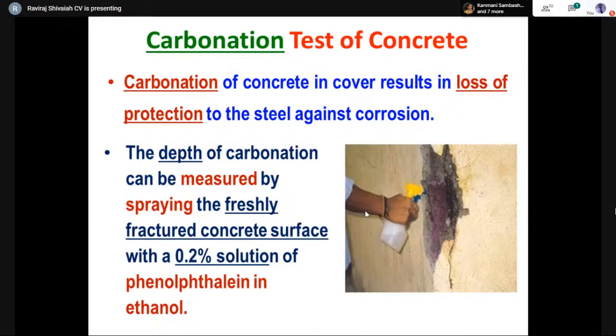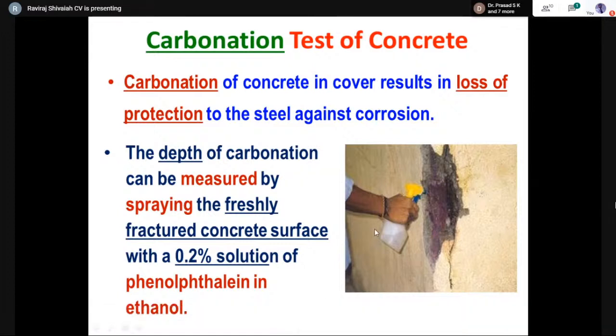Now I'm just done with the last two or three tests, very simple tests. I was talking about the carbonation test. I told you it's not good. How do we know whether the carbonation has happened or not? All you're supposed to do is break open the concrete surface slightly, about 5 millimeters, expose the concrete at a depth of 5 millimeters, take a solution of freshly mixed phenolphthalein and ethanol, 0.2% solution, and then spray it on the concrete surface. If the surface turns pink, then we need to understand carbonation has not happened. However, if it turns colorless, then we need to understand carbonation has happened.